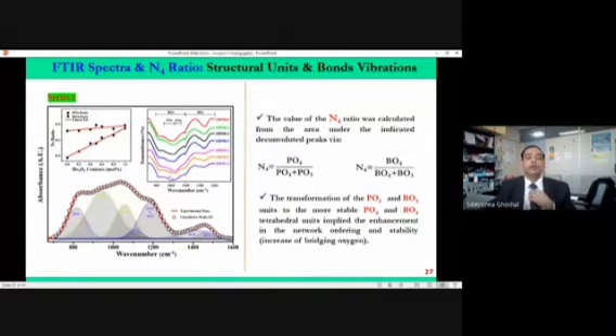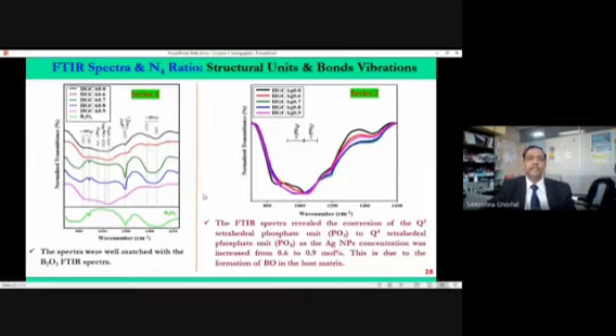How do we check? We use something called the N4 ratio. N4 ratio shows that PO4 units and BO4 units are more in the system than other units. And that clearly indicates that yes, indeed, they are there. So we are making glass ceramics which are highly stable. So this one issue is solved. The second issue: whether we have formed the right structure, or is there any impurity, any bad elements in the structure?